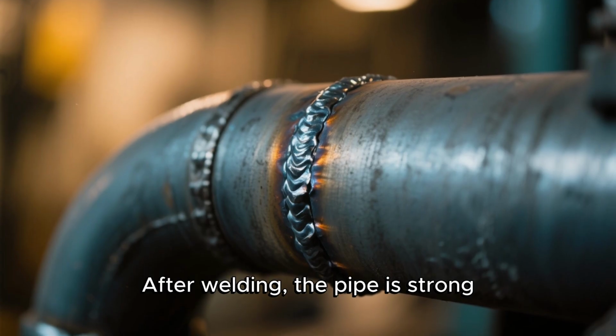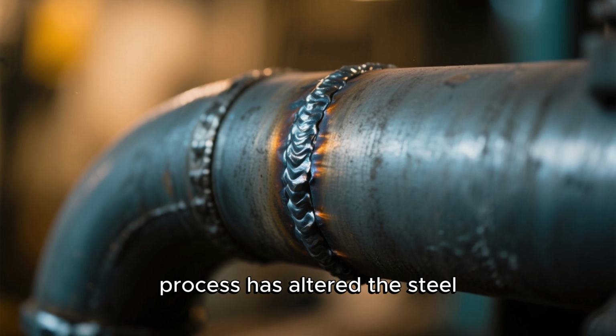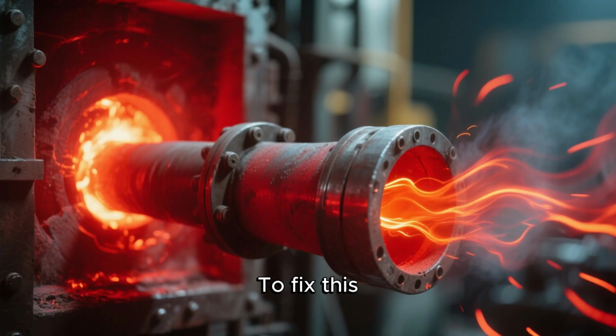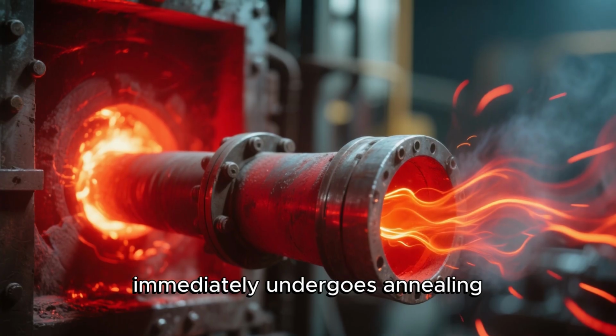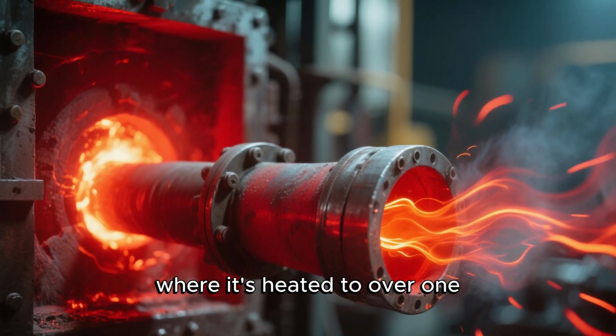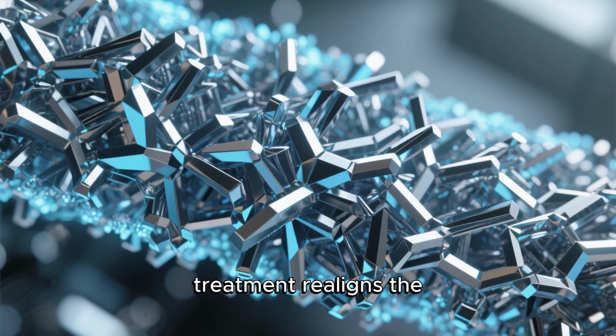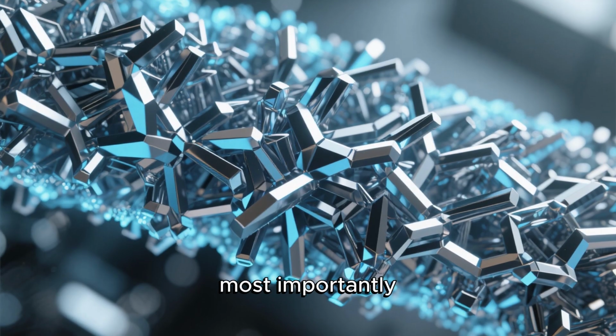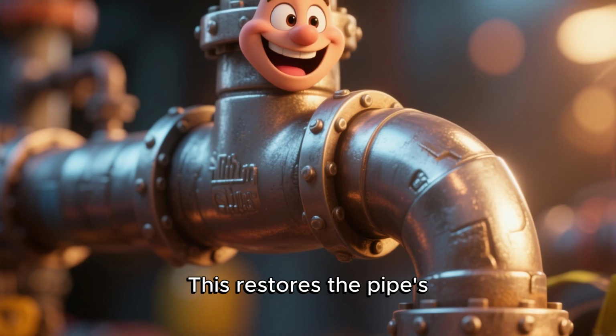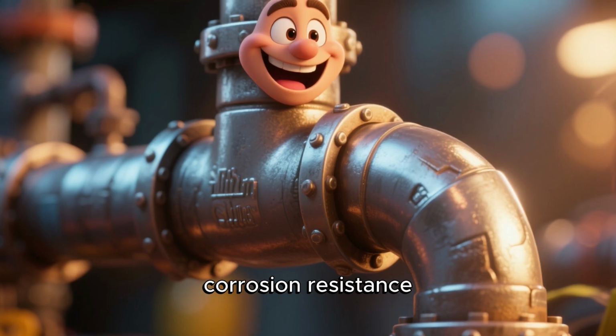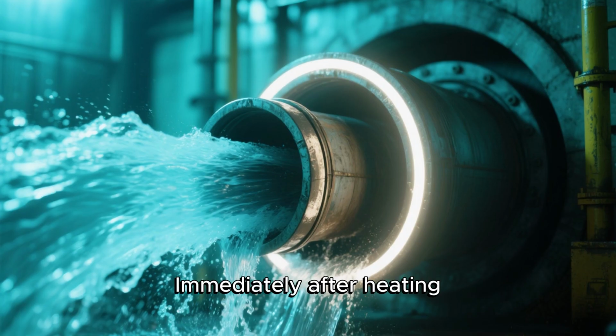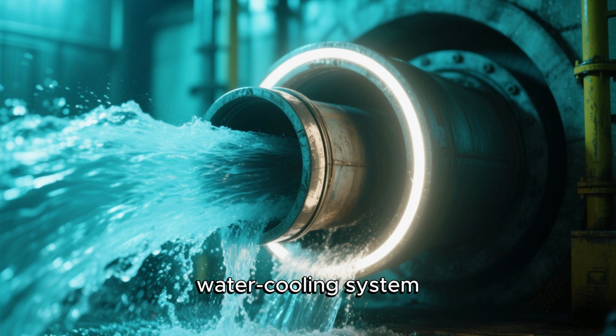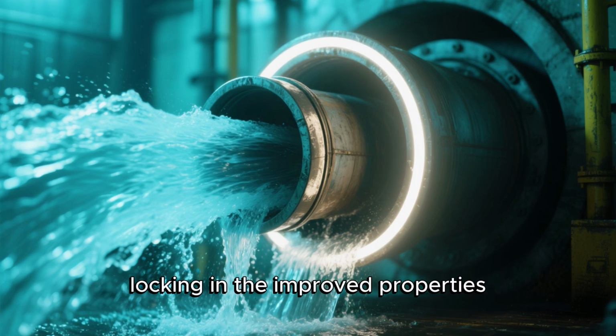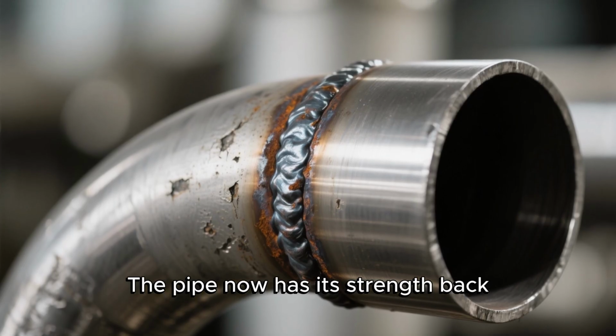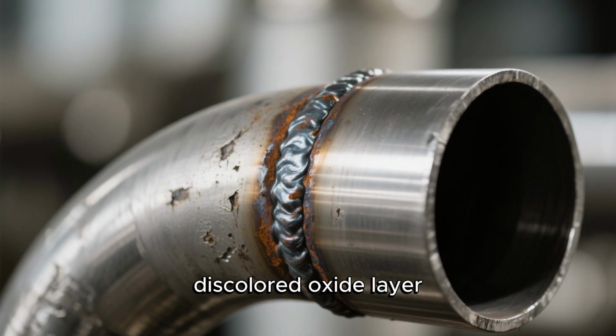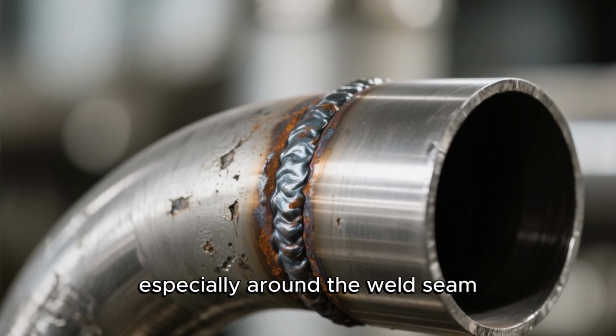After welding, the pipe is strong, but the intense heat from the welding process has altered the steel's internal structure right around the seam. To fix this, the pipe immediately undergoes annealing. It passes through an induction heating furnace, where it's heated to over 1000 degrees Celsius. This high-temperature treatment realigns the steel's crystal structure and, most importantly, redistributes the chromium evenly. This restores the pipe's full strength and its signature corrosion resistance across the entire surface, including the weld. Immediately after heating, the glowing hot pipe passes through a water cooling system, which rapidly cools it down, locking in the improved properties. The pipe now has its strength back, but the heat from welding and annealing has left behind a discolored oxide layer, often called heat tint, especially around the weld seam.